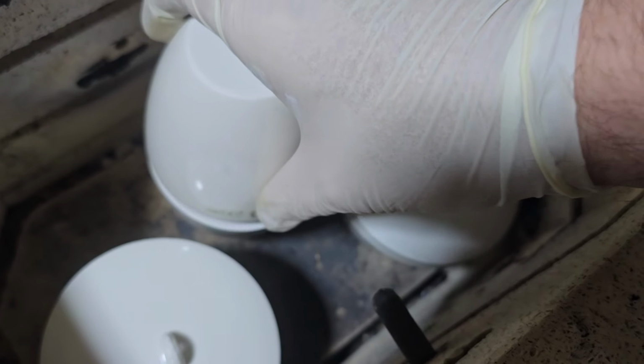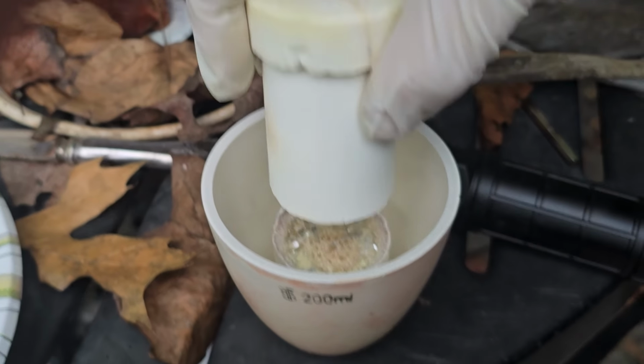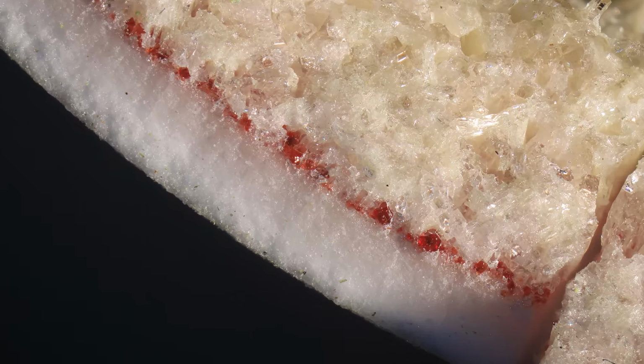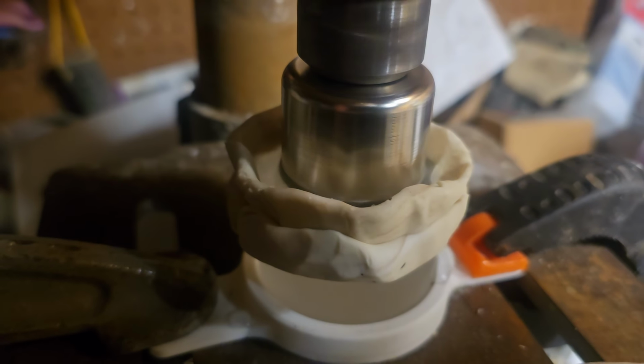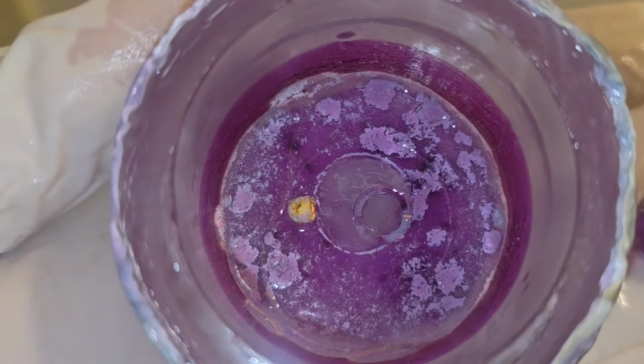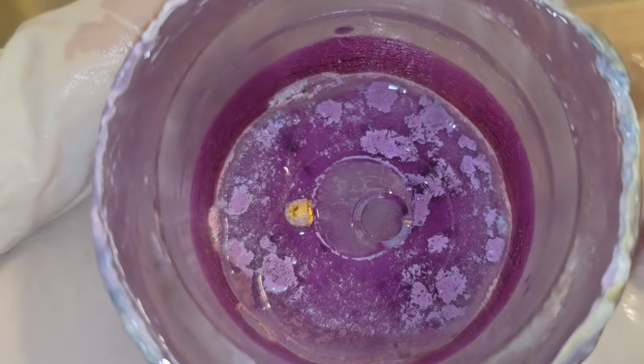I tried a magnesium oxide crucible, but the flux dissolved so much of it that I got crystals of the gem spinel, which is magnesium aluminate, instead of ruby. And also somehow a bunch of them came out blue, which is really weird. I also made a crucible from a single solid sapphire crystal, which was really cool and grew a crust of ruby on the edge, but it didn't really feel like I could grow single crystals this way. I'm sure I'll be revisiting that for future experiments though.